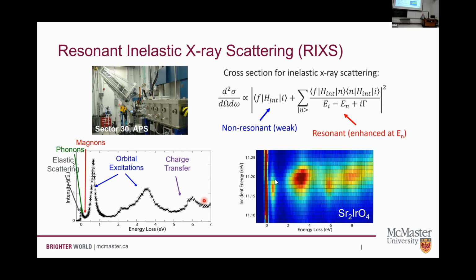So we've gotten better. And the other thing I didn't mention is that you can take advantage of not just being able to see small samples and tiny crystals, but you can also look at epitaxial films with RIXS. So you can do these inelastic scattering experiments on tens of nanometers of material, which from an inelastic neutron point of view would be impossible. But sometimes you can use the epitaxial strain to stabilize some of these things that we can't grow in bulk. So that can be another useful tool at our disposal.